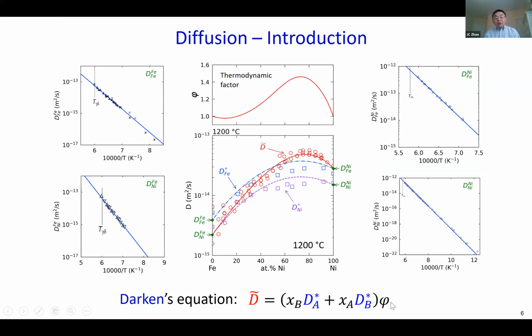So in order to do a good assessment of a binary system, you need those data for the pure elements, the self-diffusion coefficient and impurity diffusion coefficient, or dilute diffusion coefficient. One can clearly see that when you talk about the interdiffusion coefficient, it touches both sides as the impurity, not the self-diffusion coefficient. So this is an important point, right? It's the impurity diffusion that is dictating where this curve is going to land on both sides. Okay.